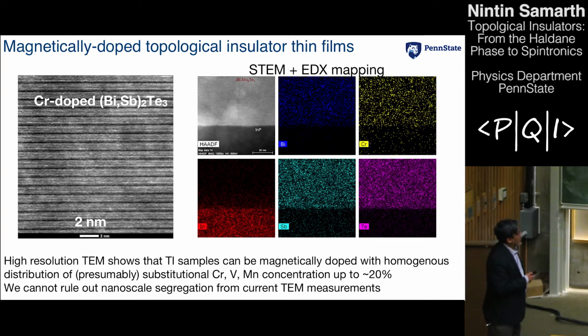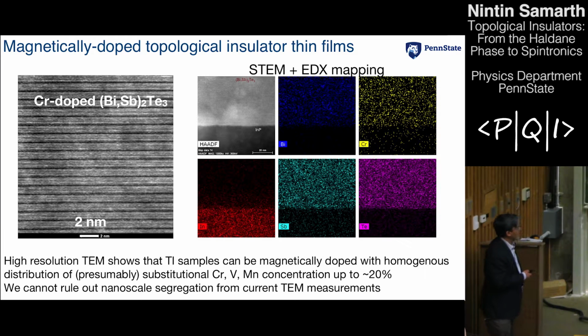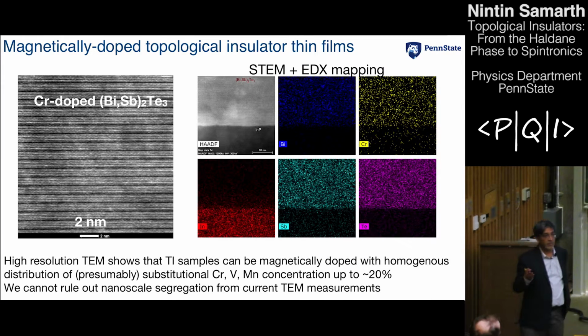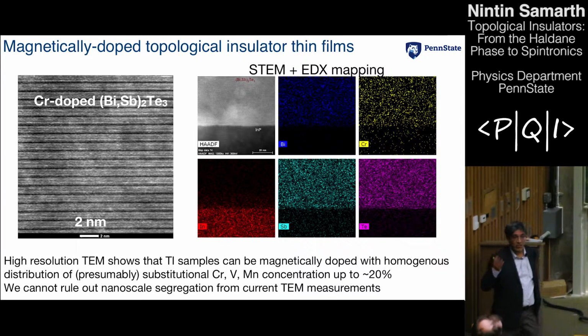And again, you have to be careful. When one shows electron microscopy images like this on this very limited spatial range, it looks like these are extremely high-quality samples, but they are not. This is just a tiny slice of an extremely disordered sample. We can map out the distribution of the magnetic elements in this. And where is chromium? Chromium is somewhere here.